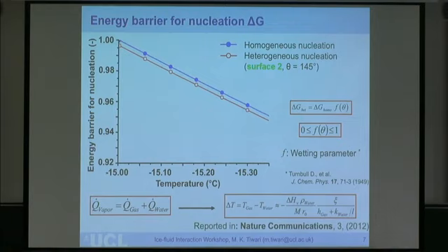So what's happening in our case is we have a slight decrease in temperature, and you will notice the scale here, it's not too much. So if I plug in the estimate, a basic scaling analysis of the temperature decrease at the top, now the top is down here, so the energy barrier is down there, whereas the bottom interface is still up there, and so we tend to see homogeneous nucleation.